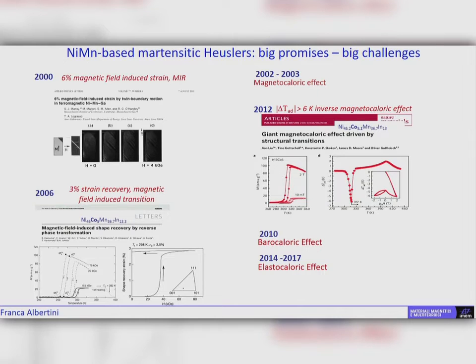And this important magnetomechanical feature is linked to the microstructure of Martensite and to its manipulation by magnetic fields. Then we can have also other magnetomechanical effects induced by field, by inducing the transition by field. Then other properties have constantly arisen along the years: magnetocaloric effect, inverse magnetocaloric effect, baro and elastocaloric effect, that is caloric response of the materials to pressure or stress.